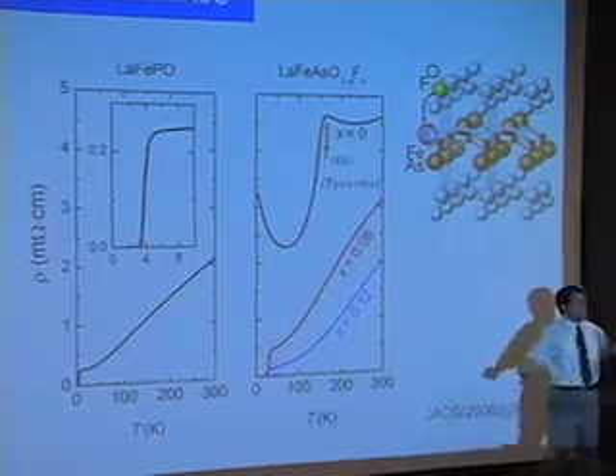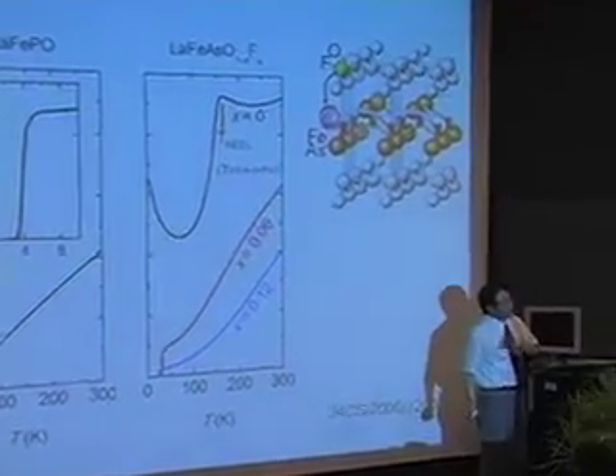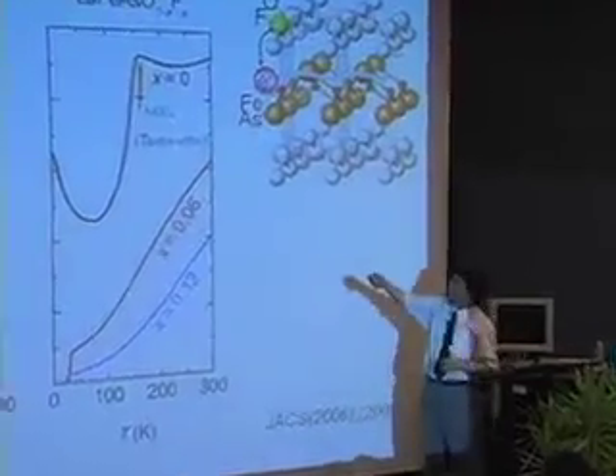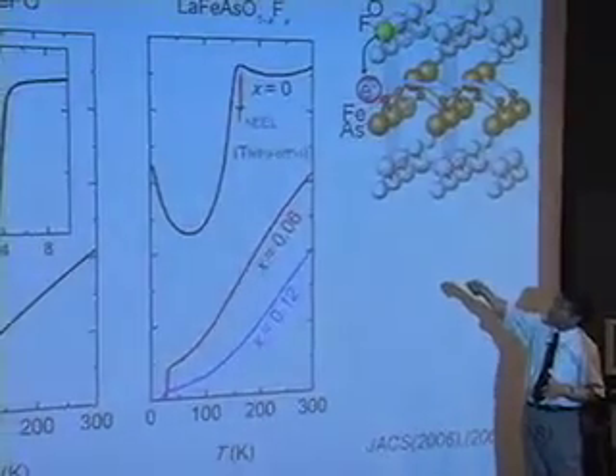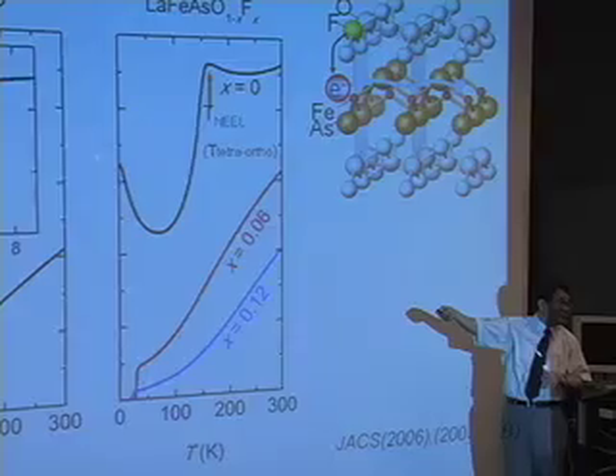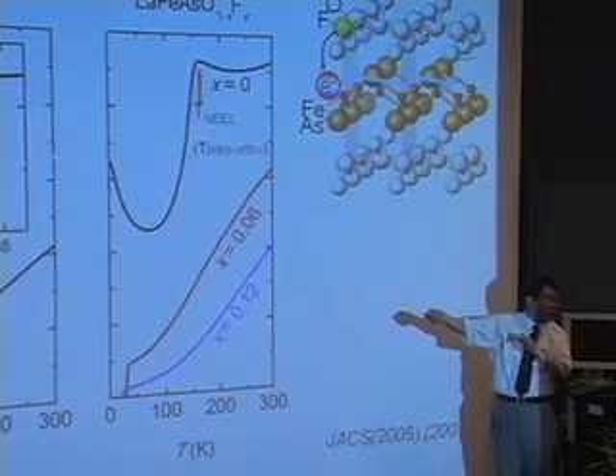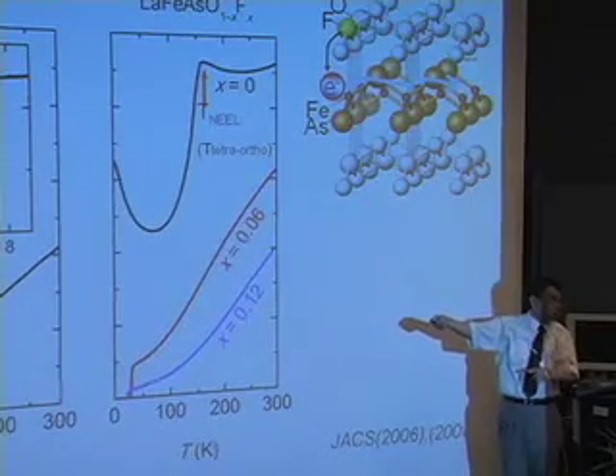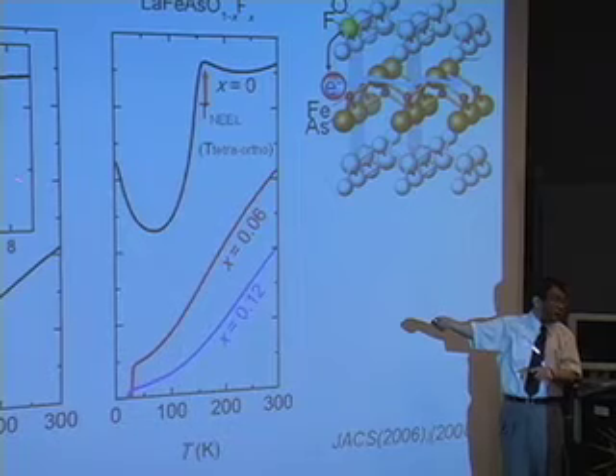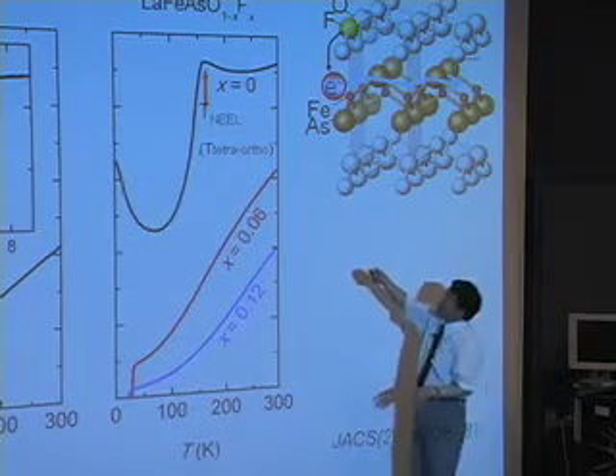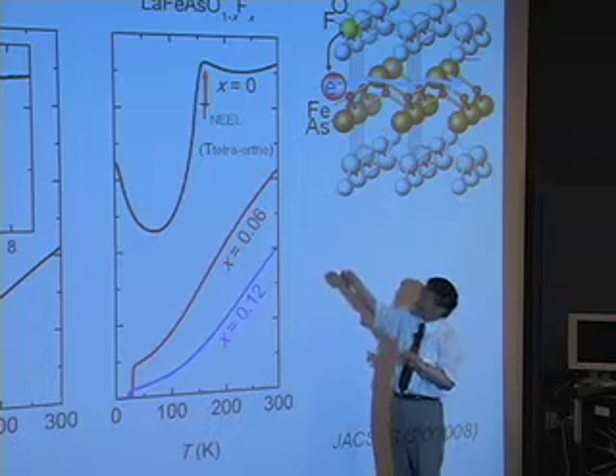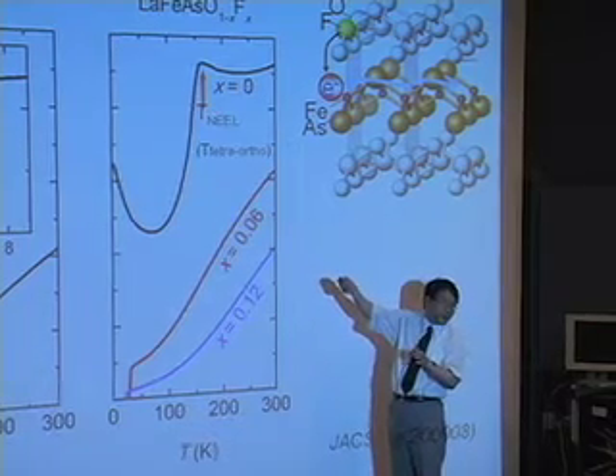At first, the student in charge of this material thought this was due to a superconductive transition—pretty high, and if true, this would be the highest Tc. But eventually this turned out not to be a Tc; it was a magnetic transition.